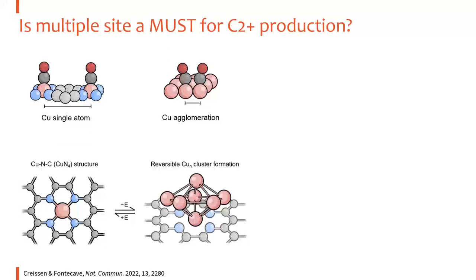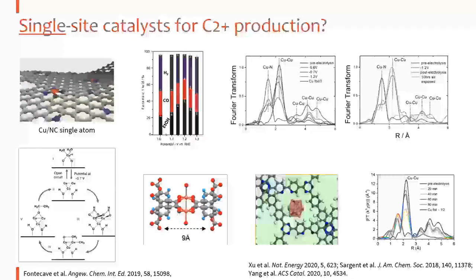This allows two CO intermediates to couple together to become the intermediate for the C2 product. And this is actually just one example to indicate how we can form the copper aggregation. So under electrochemical reducing conditions, the single atom will form copper nanoclusters, but after removing the electrochemical reducing conditions, it reverses back into the copper single atom, which is exactly the working principle for this paper.